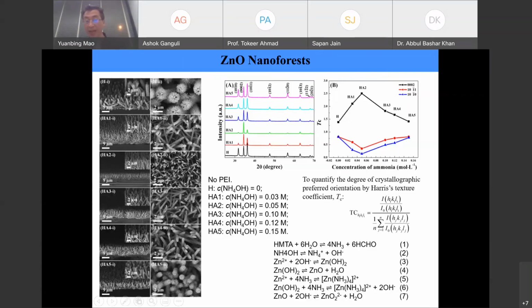So initially, because we didn't add PEI and ammonia, the HMTA plays the role, right? Basically, it generates ammonia, and that provides the basic conditions. Then zinc reacts with this and generates zinc hydroxide. It decomposes into zinc oxide. So if we have a basic condition that is not too strong, then we can generate zinc oxide, right? But then we add more ammonia, and that's when the aging happens, right? And PEI also has a similar function, while PEI can also act as a capping agent. So that's where the synergistic actions happen.